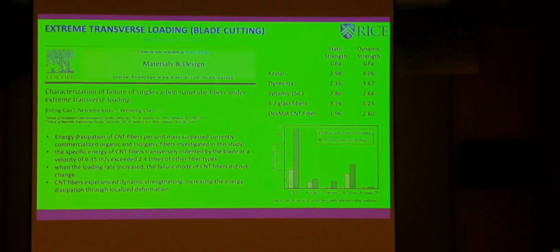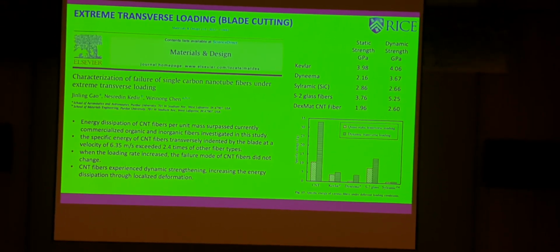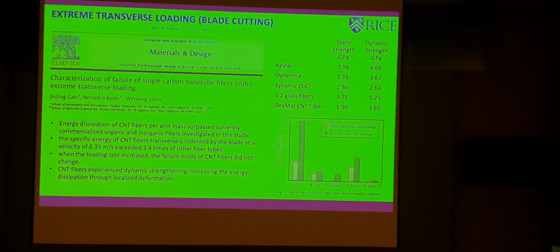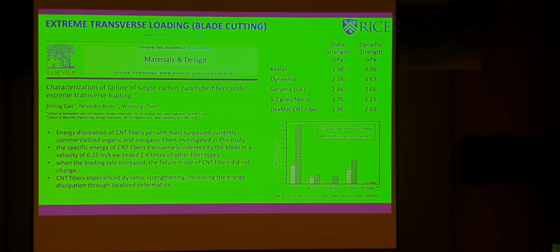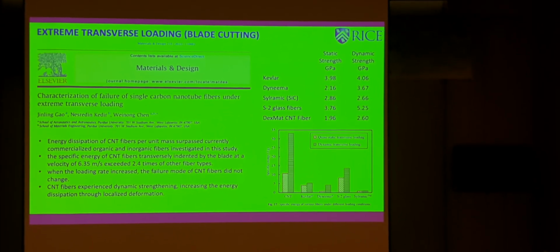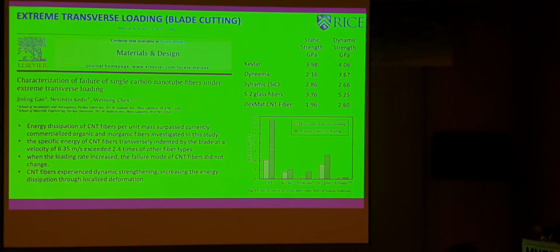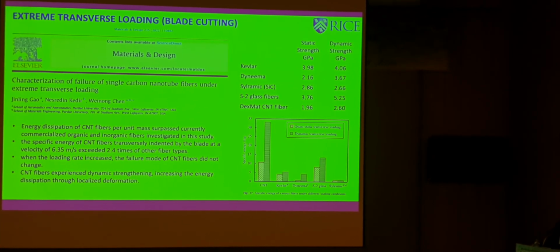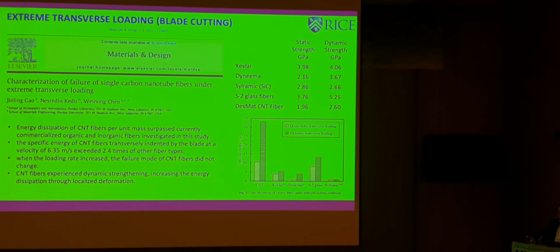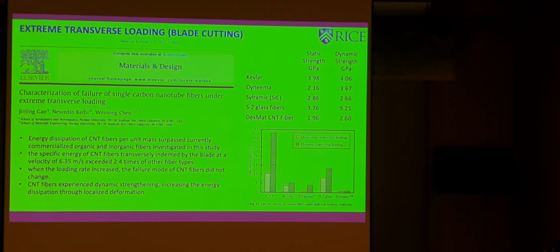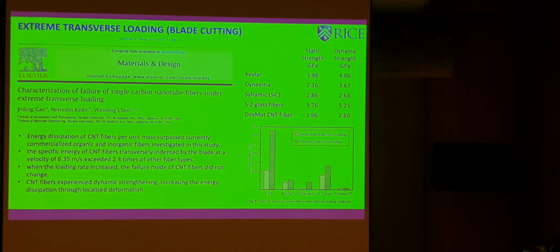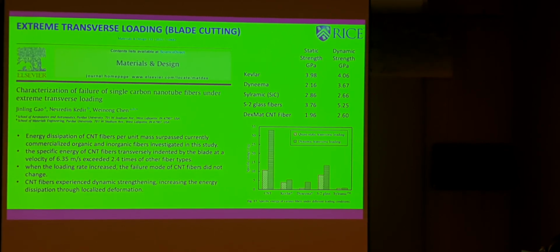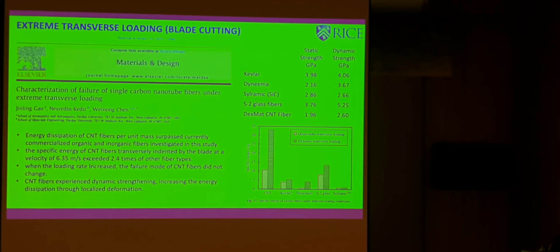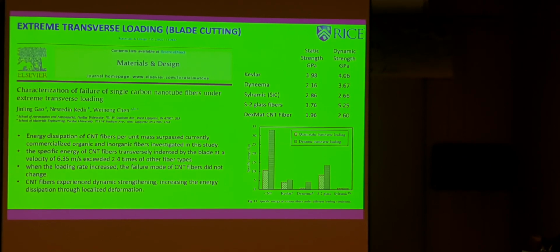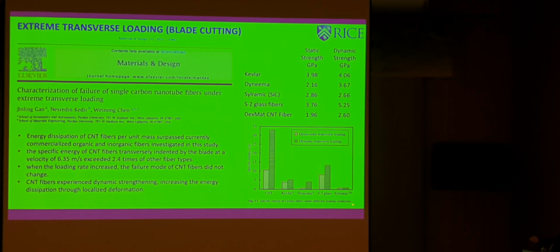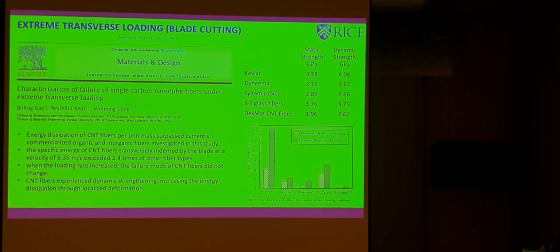This is another one. These are people who saw DexMat videos where they throw axes at the nanotube fibers, and the axe can knock out the nanotube fiber. So this group bought some of the fiber. It's Wenning Chen from Purdue, and looked at the blade cutting and saw that the CNT fiber had significantly better blade cutting resistance than Kevlar, the S-glass, and ceramic, which is a silicon carbide fiber.